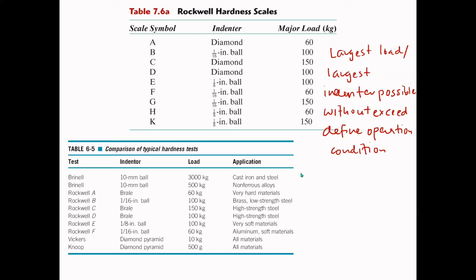These conditions include test specimens that are below the minimum thickness for a depth of indentation, a test impression that falls too close to the edge of a specimen or another impression or indentation, or testing on a cylindrical specimen, like this. In addition, the test axis should be within 2 degrees of perpendicular to ensure precise loading. And there should be no deflection of